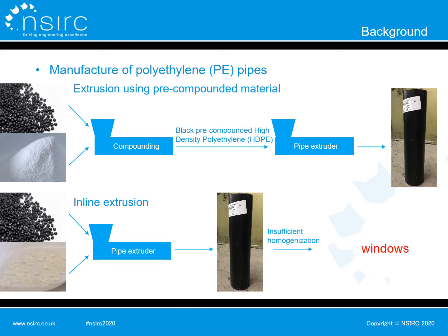The existence of the windows may induce stress concentration, therefore influencing the butt fusion joint integrity of polyethylene pipes. What is more, if the bond at the interface between windows and the black regions is weak, the butt fusion joint integrity of PE pipes can be significantly influenced. In addition, the black regions with high carbon black concentration may need to be concerned as well.